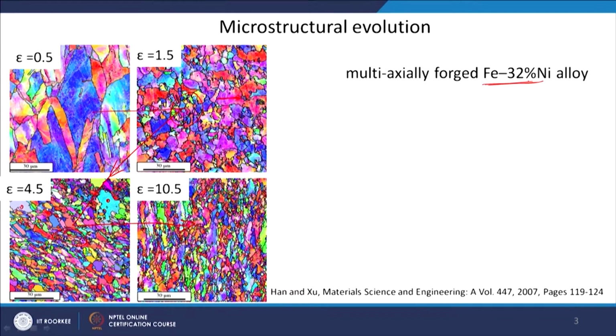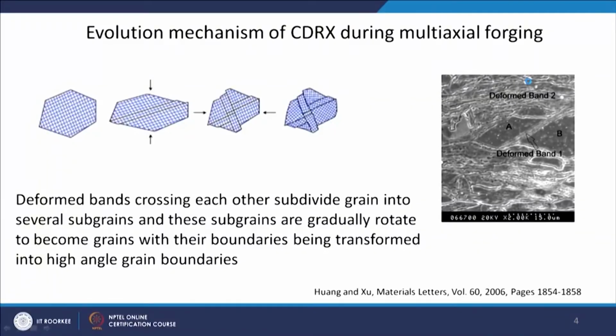The grain refinement is usually through dynamic recrystallization, and slowly you can see the effect of strain on the recrystallization process, the grain refinement. Now, how this recrystallization takes place in multi-axial forging is shown schematically here, one mechanism. You have this initial grain. When you are deforming from here, it is getting elongated in this direction. There are also some deformation bands which are being introduced in the material during the deformation process, usually at around 35 to 45 degrees to the forging direction.